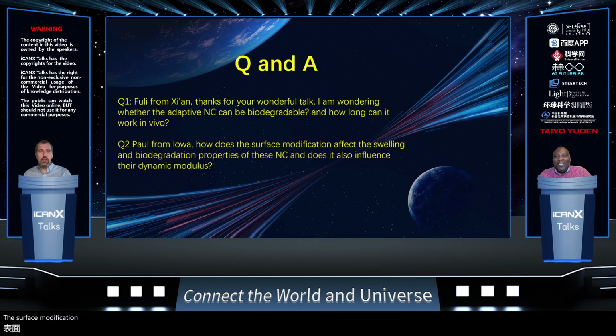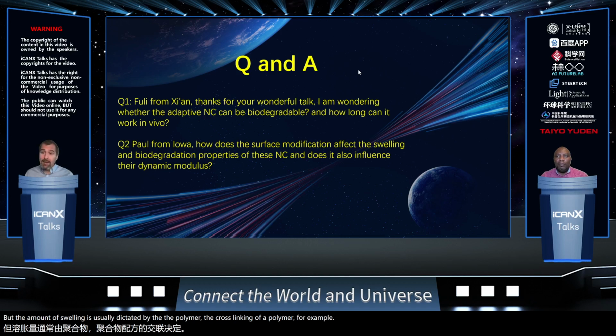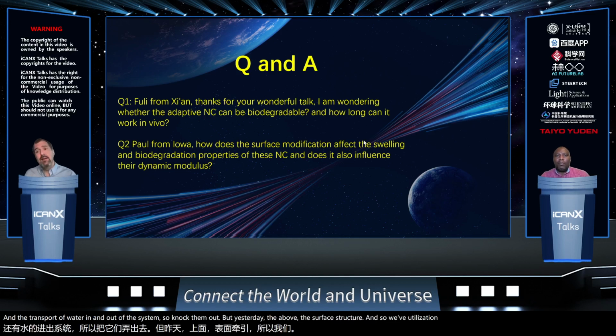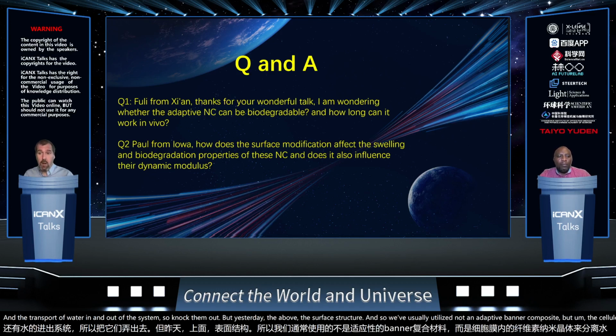The surface modification, I would say, does not directly affect the swelling or the amount of the swelling. The surface modification does affect the transport of water in and out of the system, but the amount of swelling is usually dictated by the polymer, the cross-linking of the polymer, for example. That being said, surface modification does affect the speed of the swelling and the transport of water in and out of the system. So not the amount, but yes, the surface charge. And so we've utilized not an adaptive nanocomposite, but the cellulose nanocrystals within membranes for water separation, for example, or water transport through systems.